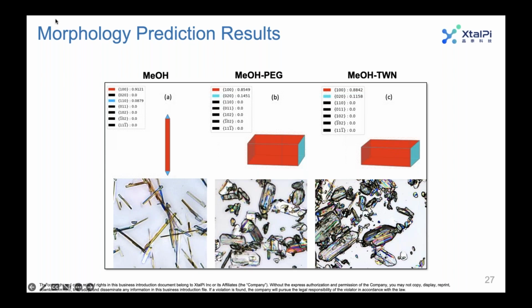So the first is if we look at metformin HCl grown in a solution of MEOH. This is a PLM image below that was obtained from the crystallization experiments. And we see that these are very needle-like crystals, and the calculations are able to reproduce that qualitatively very well.